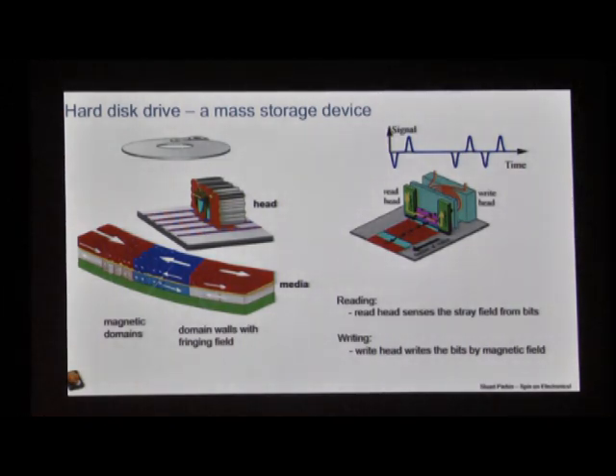So now, why was this important? This spin-engineered spin valve structure we could then use to detect magnetic fields. And some of you may be familiar with a magnetic disk drive. Basically, you have a glass disk which is rotating at high speed below a device that is used to both write and read information which is stored in a magnetic film, the magnetic media, which is deposited on this glass surface. So the information is really encoded not in the magnetic regions themselves, but as the boundaries, or the domain walls, or the transitions between magnetic regions with magnetization pointing here to the right or to the left.